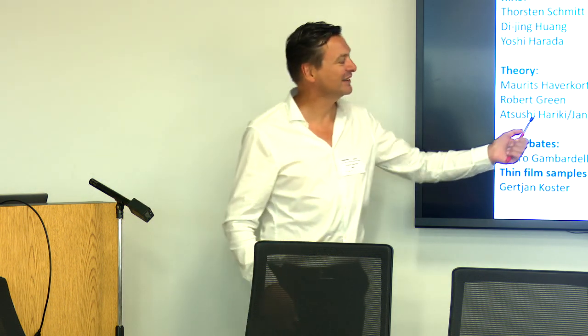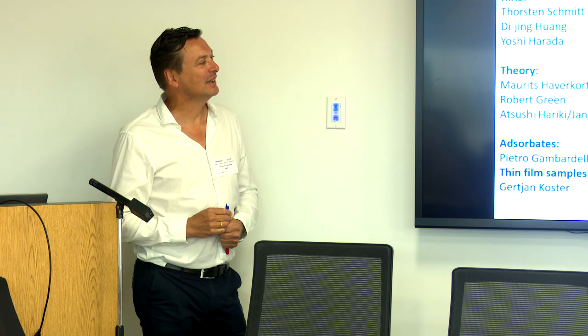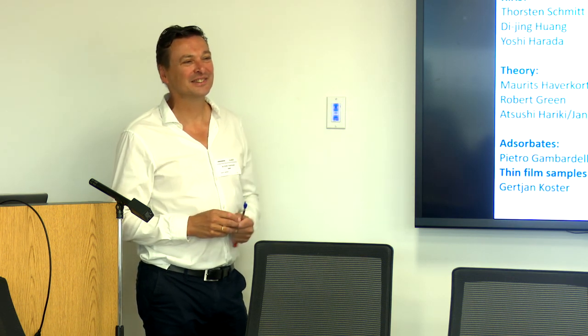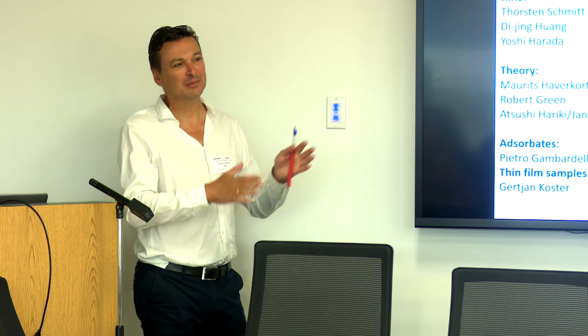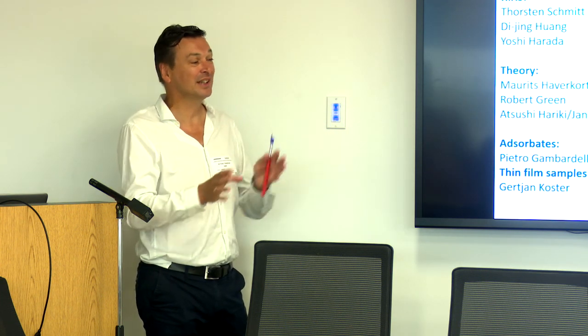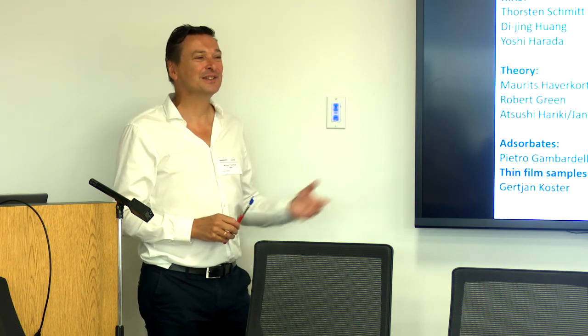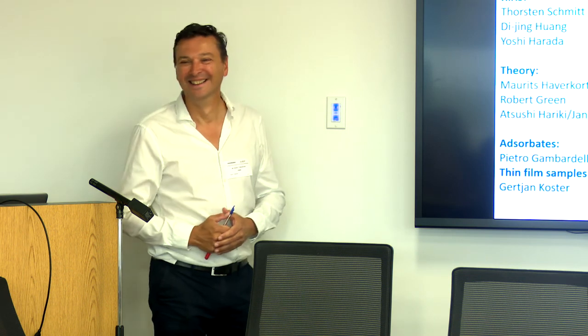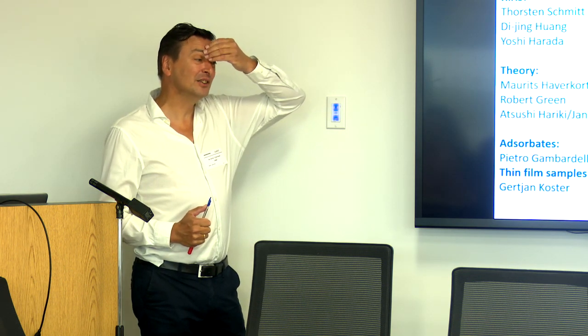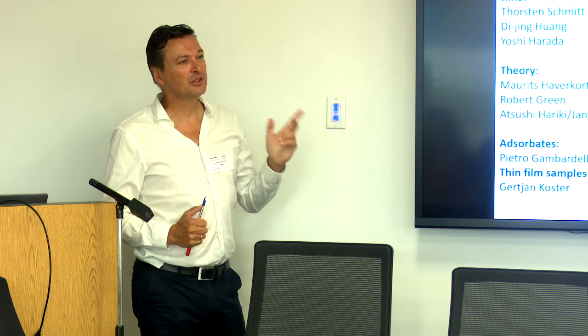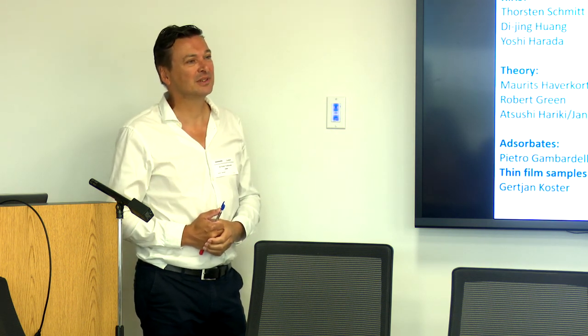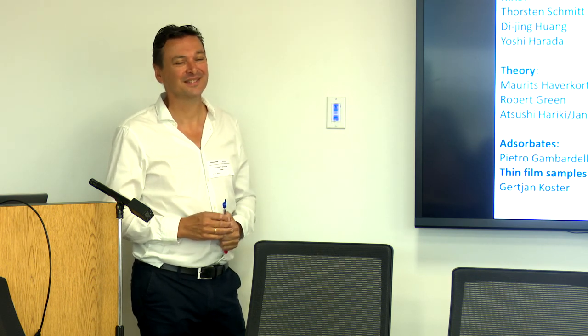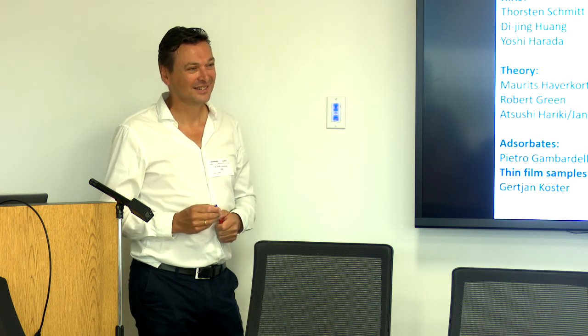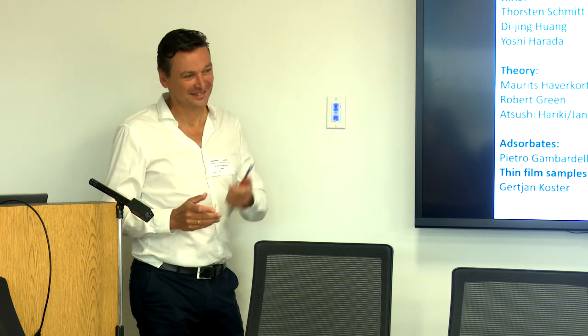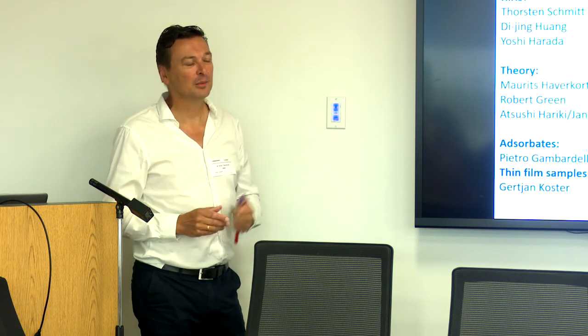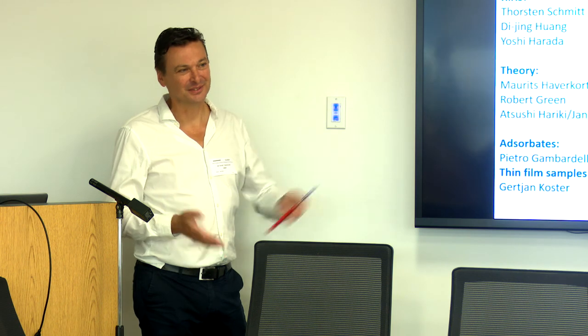So Jan Kuneš and Susie are now working on the data, but it looks like it's a little bit more complicated than the initial calculation, because this was data with 100 millielectron volt, and that seemed ideal for their calculation. We took the data and they did calculations and it fitted perfectly. But now with the high resolution data, it's less perfect. Although they are kind of first principle calculations, there's still the Hubbard U, which is not first principle, and that can modify things. That actually relates to the other conversation also. With the F2 and F4, I don't know, it's not obvious to me. Actually, the Hubbard U determines if you have an excitonic insulator or not, at the zeroth order, right?